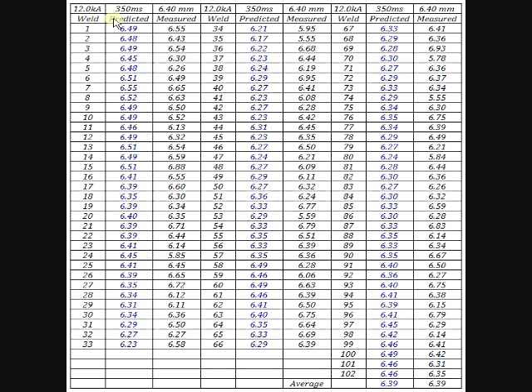This is a repeatability test or consistency test. The welder is programmed at 12.0 kiloampere, 350 milliseconds, with a 6.4 millimeter weld cap. And this is in the medium temperature welds. So we expect the predicted and the measured nugget close to 6.40 millimeter.